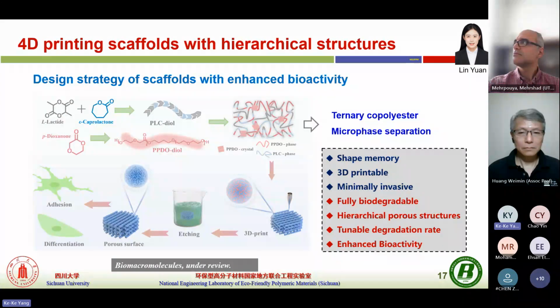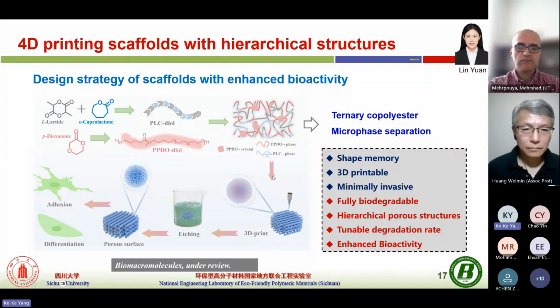First, we produce by FDM printing to get the microporous scaffold, and then we put it in alkaline solution to accelerate the degradation due to the microphase separation morphologies. It can show different degradation rates, allowing us to create microscale pores on the scaffold, which leads to enhanced bioactivity in this scaffold.